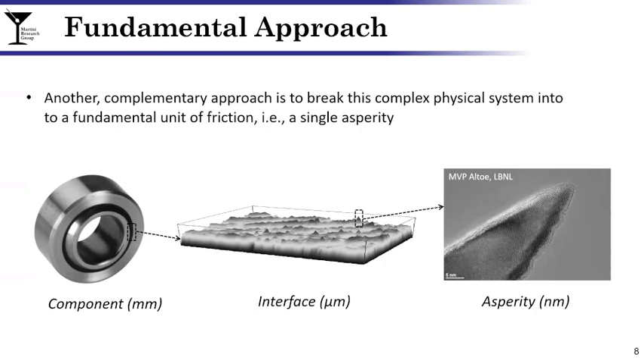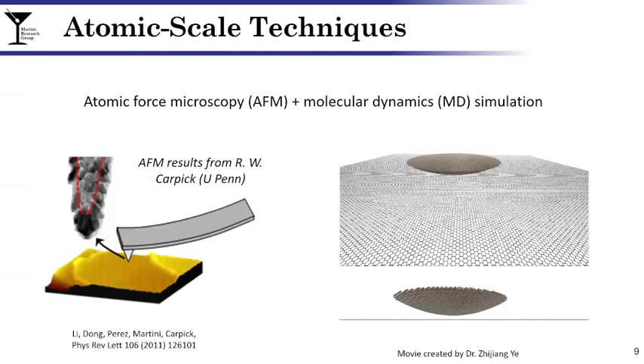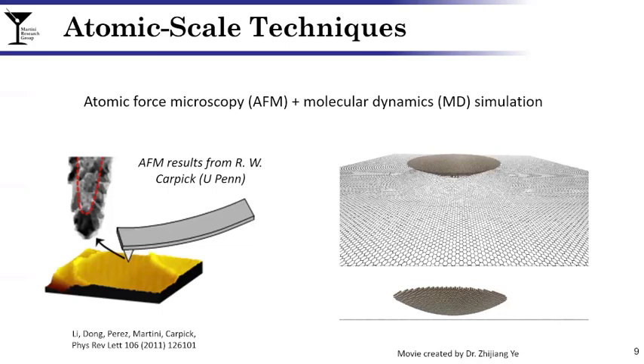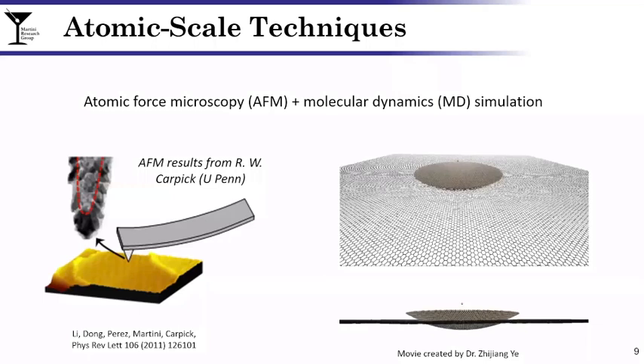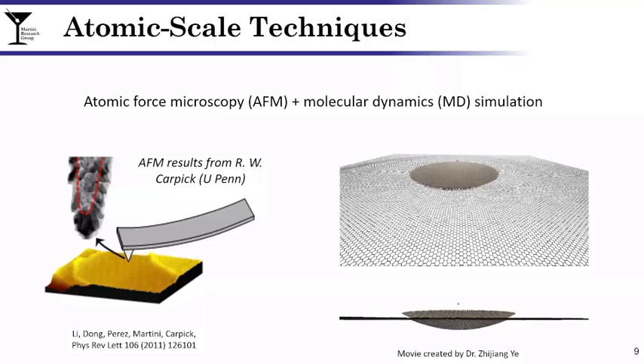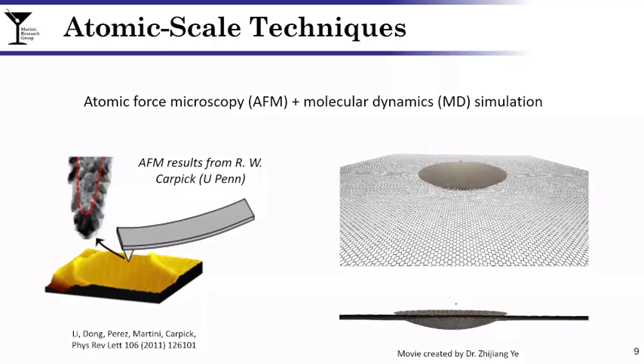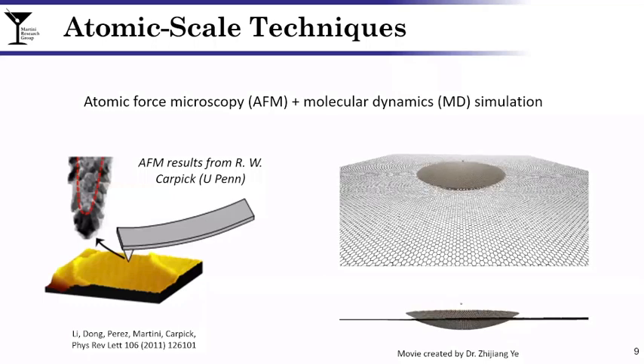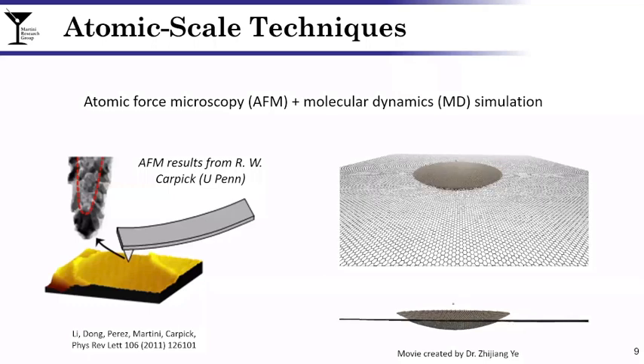In terms of research, the single asperity studies are realized primarily using two tools. The experimental tool is the atomic force microscope, where we have a nanoscale probe sliding along the surface, where that nanoscale probe is your single asperity. And I will again mention up front that the AFM results I'm going to be showing to you today are from R. W. Carpick at UPenn. The AFM experiments are often complemented by molecular dynamic simulations of the apex, or just the bottom of the tip, and the surface on which you're sliding. So together, these two research tools can be used to fundamentally understand friction at the atomic scale.